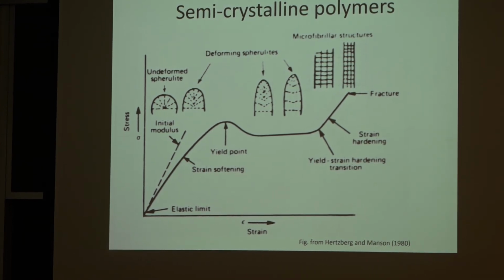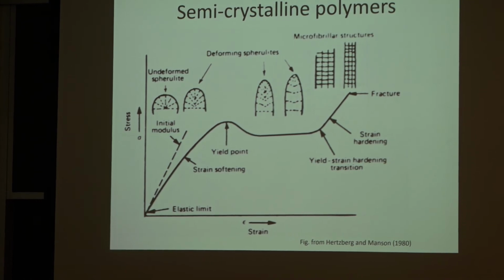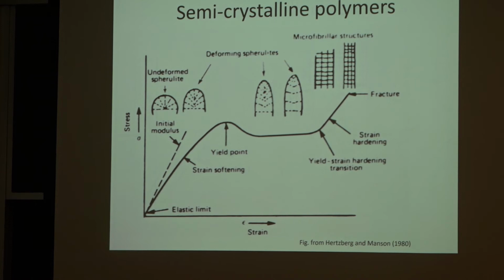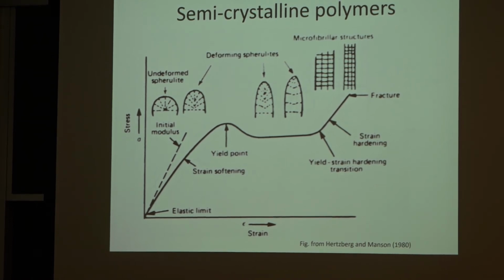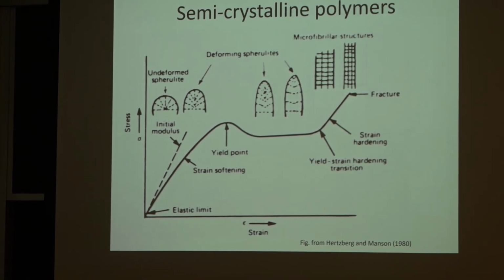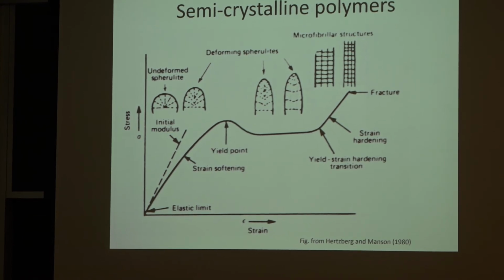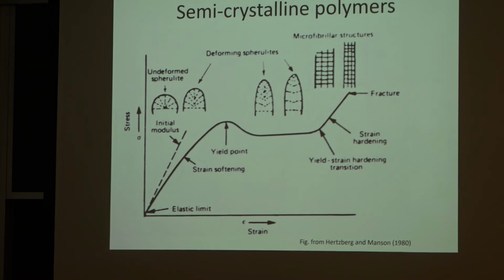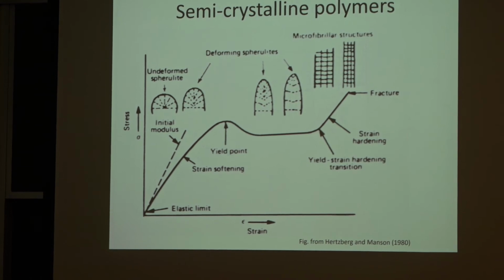Now, you don't have to take my word for it, because to the extent that a plastic bottle is relatively soft, a nylon cord or a polyethylene rope is pretty stiff and strong for the same amount of material because it went through this transformation. So in deforming it, you went from the as-cast structure to something that is fibrillar and very oriented, essentially almost like a glass reinforced plastic internally, where the crystallites make that bridge and do carry the load. You don't have a load path now where you're just going through the amorphous zone.